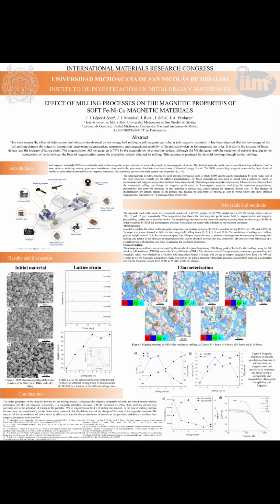These ferromagnetic powders are obtained by a large number of processes used to obtain soft magnetic materials, and can be manufactured by some routes. One of the most important recently is additive manufacturing. These materials are also used mixed with a polymeric matrix to manufacture soft magnetic composites that have three-dimensional isotropic ferromagnetic behavior. It has also been observed how mechanical milling can change the magnetic performance in ferromagnetic particles, modifying the saturation magnetization, permeability, and coercivity, produced by the reduction of particle size, which reduces the magnetic domain size. The changes of magnetization are directly related to the particle size, reduced by long milling times, as seen in works where they have obtained ferromagnetic nanoparticles and amorphous powders.